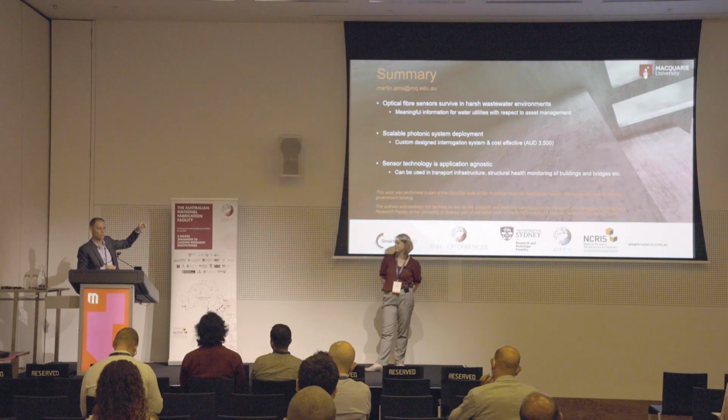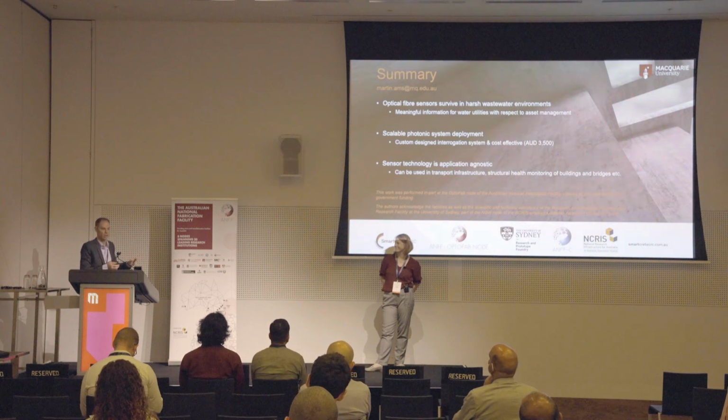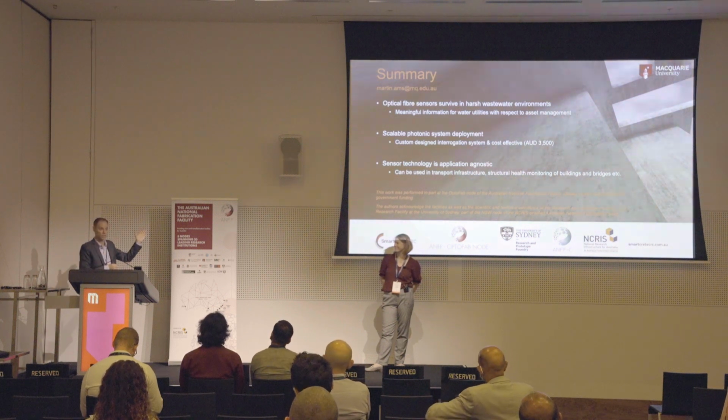Am I doing chemical sensors? That can all come down to how you transduce or coat an optical fibre to measure what you want to measure. You could coat a fibre in, say, palladium and measure H2 gas concentrations, for instance. You could coat it in other polymers, say hydrogels, and maybe measure pH. I have done some work in some of those things. They don't suit too well to high pH concrete or low pH acid. Some of those coatings can degrade, but in other environments where that's not an issue, it may be acceptable.